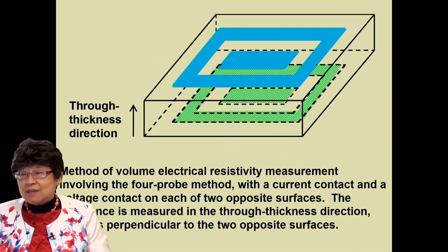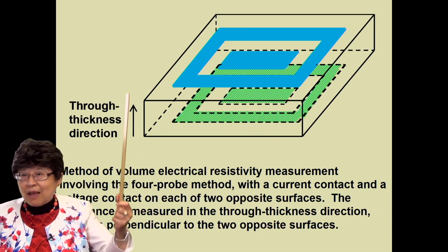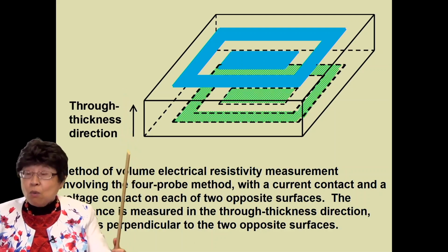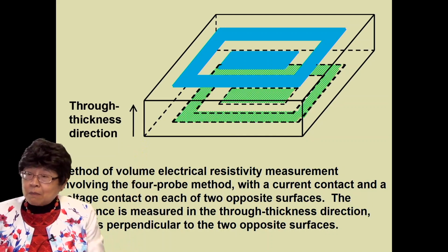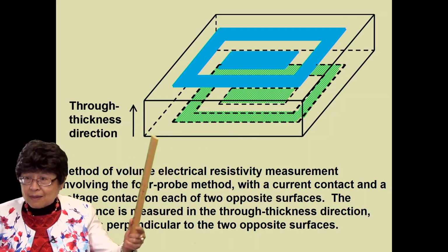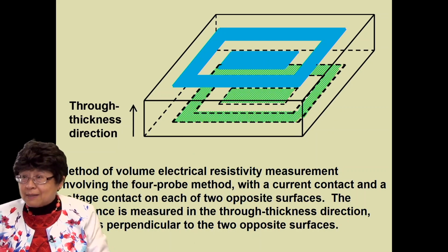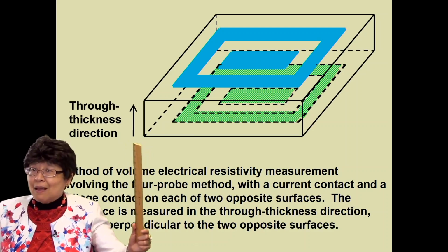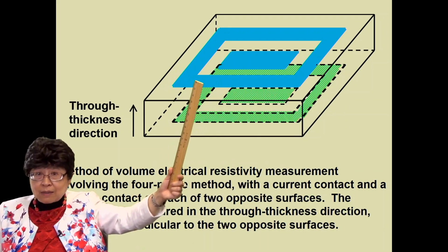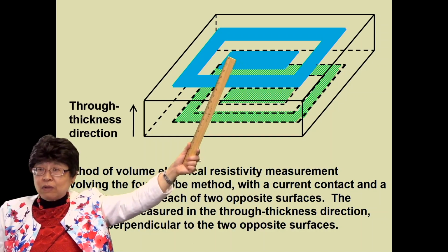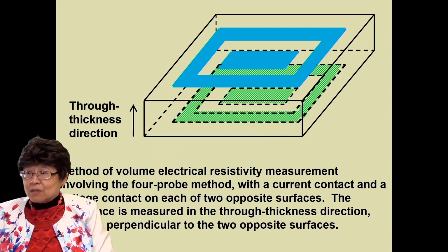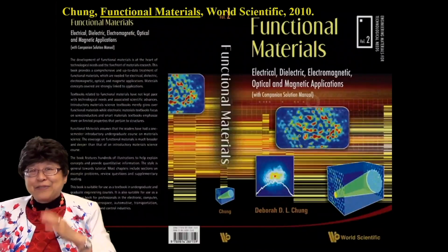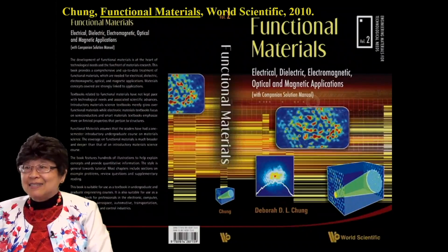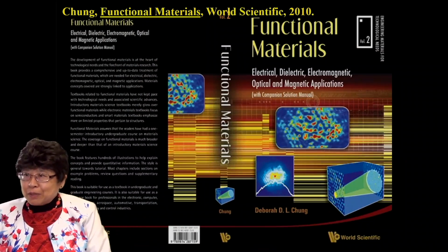Now, if one wants to measure the resistance along a direction that is very short, like through the thickness of a slab, it's so short that it would be difficult to put 4 contacts along 4 horizontal planes. When that is the case, it's possible to use this non-ideal geometry of the 4-probe method. Namely, you have 4 contacts, 2 on each of the 2 opposite faces. The outer one is for imposing the current, and the middle, smaller one is for measuring the voltage. So it can be done, even if the material has a short dimension. A lot of these techniques of electrical measurement are described in my book called Functional Materials.